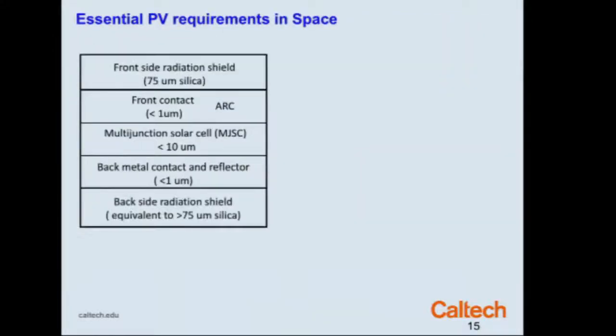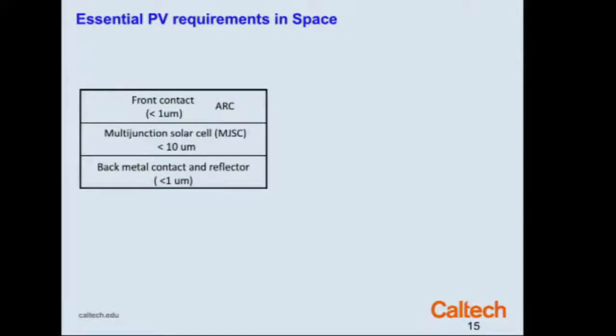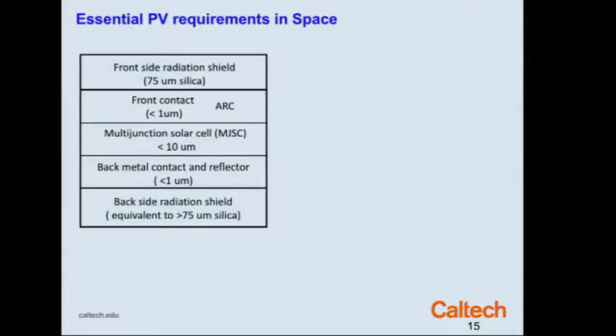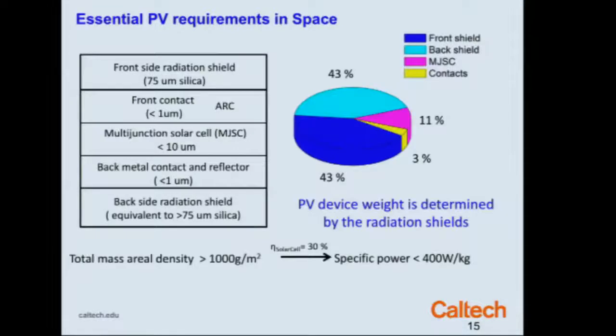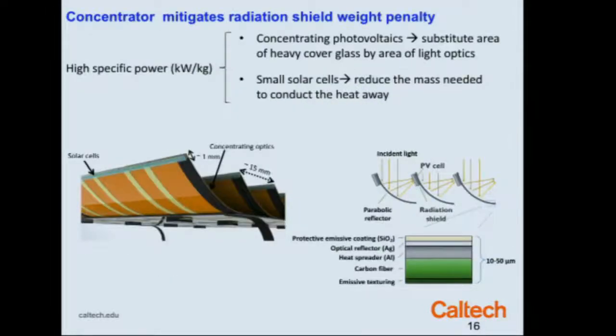So this illustrates it dramatically. The solar cell itself consists of a front contact and a metal back contact, but I have to put shielding on top and the bottom, and the shielding represents, in this pie chart, most of the mass. That would limit the power density I could get to about 400 watts per kilogram. And our goal is to get to 1 to 20 kilowatts per kilogram. So therefore, we're going to go to concentration. And why would we do that?